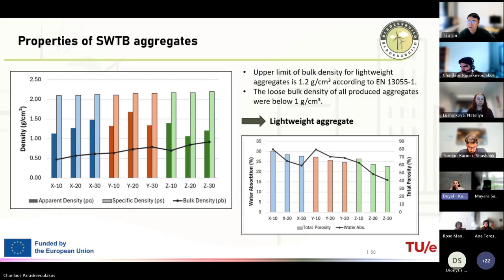There are other important parameters for lightweight aggregates, which are water absorption and porosity. Usually they are connected to each other. According to the literature, I also compared my results with other lightweight aggregates in use in the industry currently. I see that the water absorption and the porosity are in line with the artificial and lightweight aggregates in use in the industry.